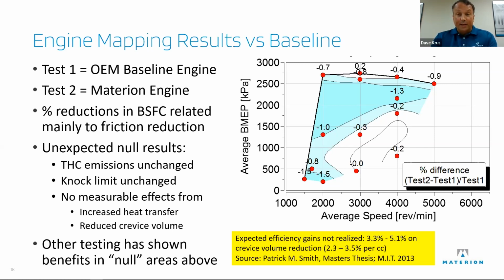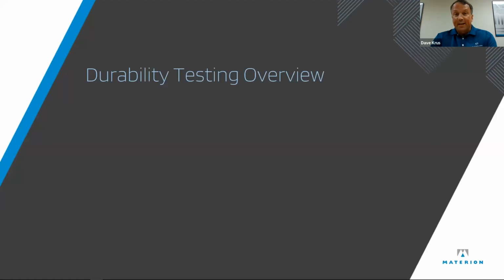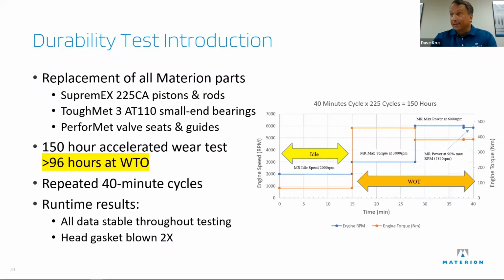So what we did after that was see, will it last? How long can this stuff last? Are these racing materials good enough to run for OEM durability lifetime? And Cosworth picked a brutal durability test to put on. So they replaced all the Materion parts and had a new block to start fresh. And this test is 150 hours and it totals greater than 96 hours at wide open throttle.